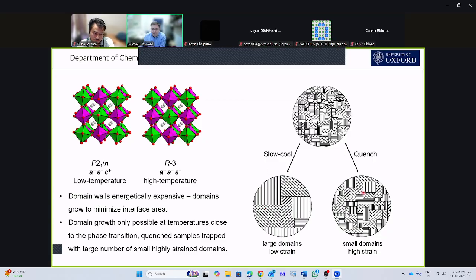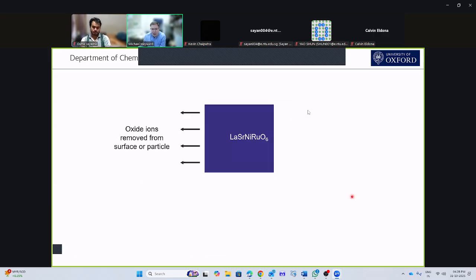But if we quench quickly, we don't spend any time at all in that domain growth region, and we get lots of small domains and high strain. So you might then ask, well, how does that lead to the difference in reactivity? Well, what we can think about now is a cartoon of the reaction. So here, this purple block is our sample of LaSrNiRuO6, our starting material. And what we're going to do is remove oxide ions from the system, but I have to remove them from the surface. I can't just teleport them out.